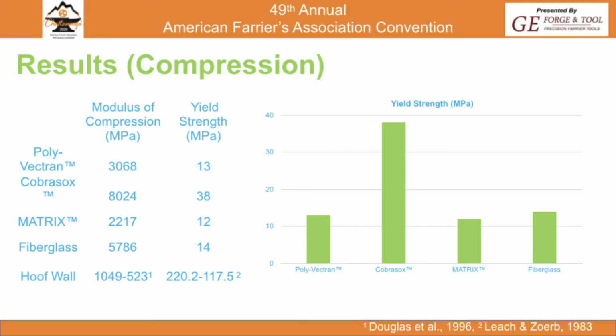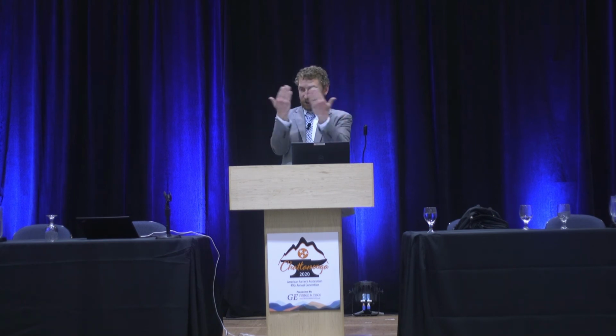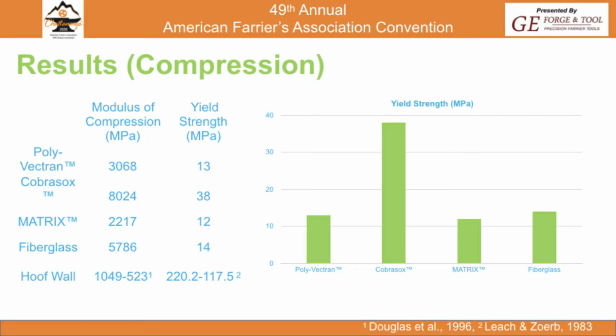And so you'll see as we go through those results, and we look at the modulus of compression, which again just shows how stiff it is. All of them again are stiffer than hoof wall, but unfortunately now you'll see the yield strength is markedly lower than hoof wall. And that's a result of the materials just delaminating. So they're not very strong in compression. And so I really think the compression on the toe crack itself, so the fact that the scissors close so hard, and these repair materials are very difficult to stop or limit that from their delaminating or the stress in which they just take the strain, is again far lower than hoof wall, which is why I think oftentimes we've had to repair them with the metal materials.